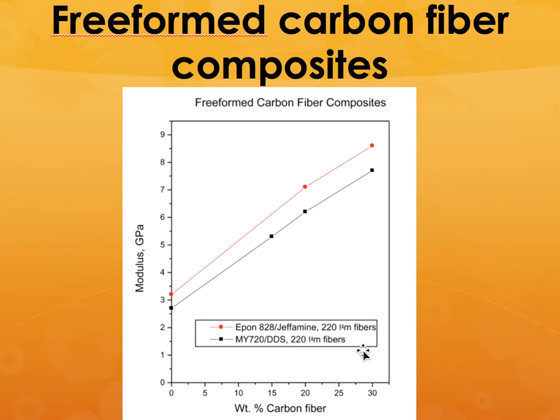I mean, these are pretty large size fibers, but still, just to show that, with no fibers at all, you have approximately 3 gigapascals modulus. But by adding about 30%, you can increase that to about 8.5 to 9 gigapascals. So you can see that it can strengthen it, or stiffen it, by approximately 3 times.